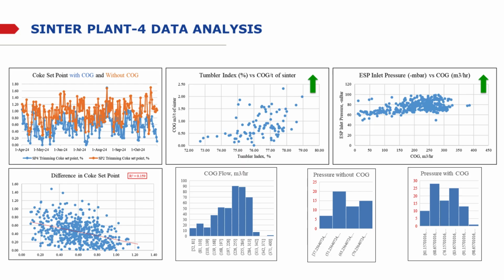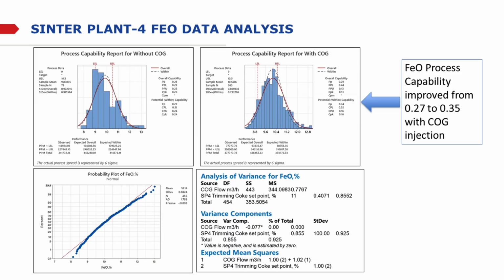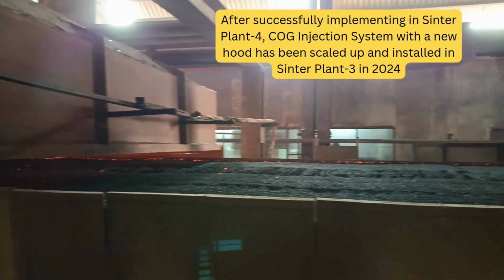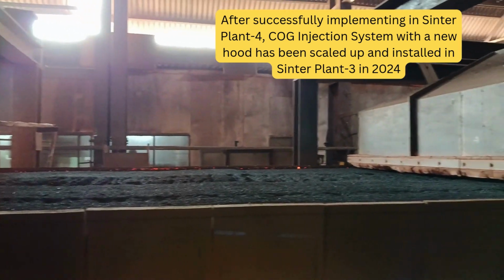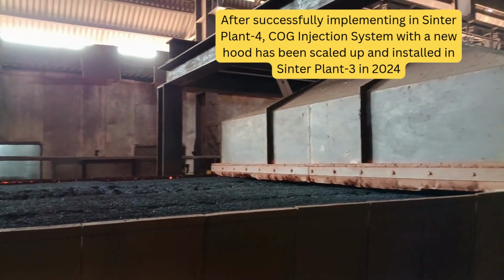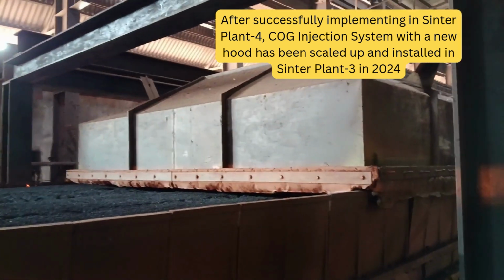Sinter plant 2 and 4 consume the base mix from a single source. With COG being injected, sinter plant 4 consumed less coke, as seen by the coke run chart. The tumbler index and suction increased due to COG. Analysis of variance shows the process capability of FeO increased from 0.27 to 0.35. After successfully proving the industrial scale concept, the COG injection system was installed in Sinter Plant 3, which is double the capacity of Sinter Plant 4.